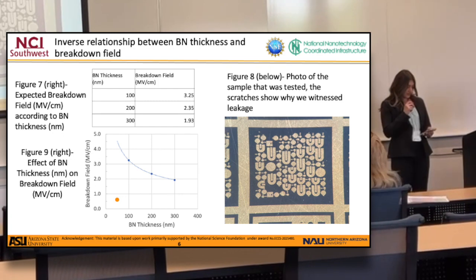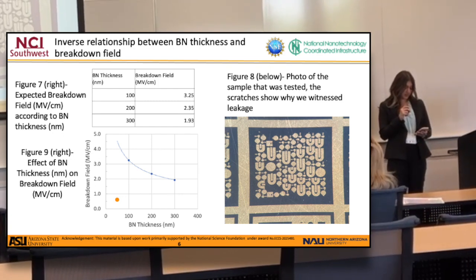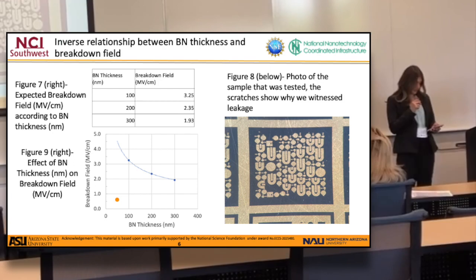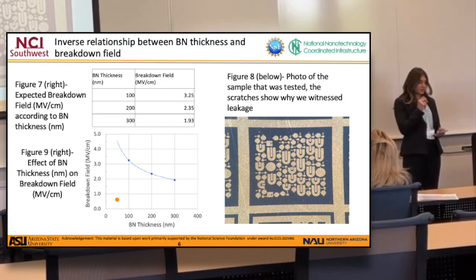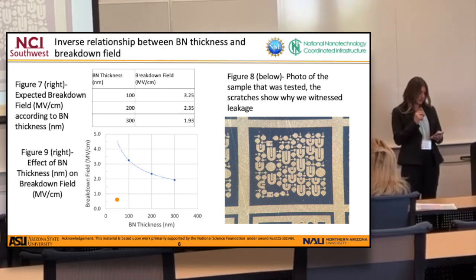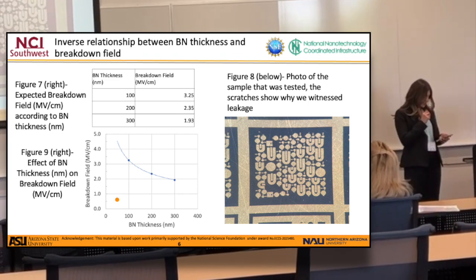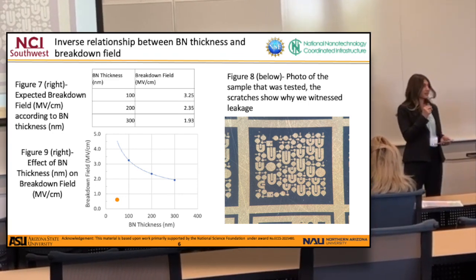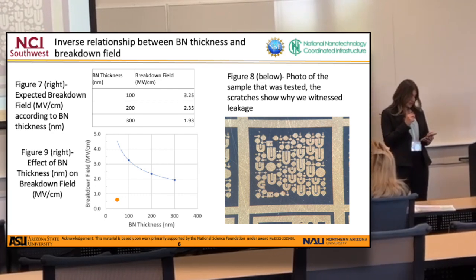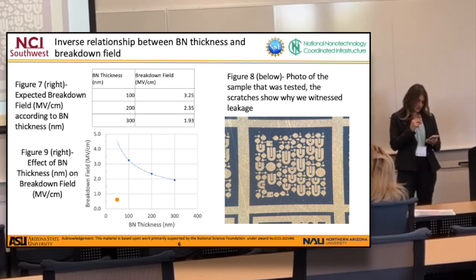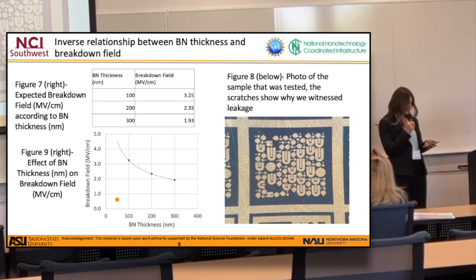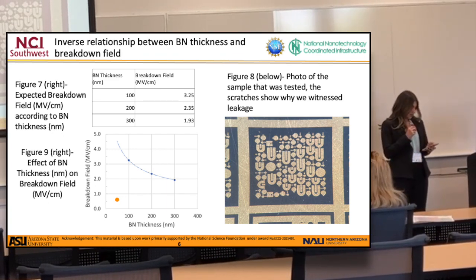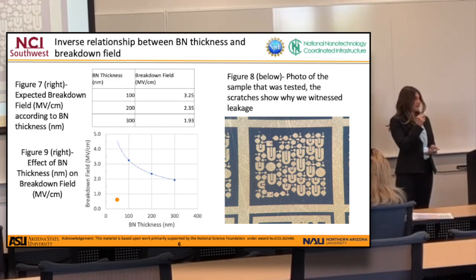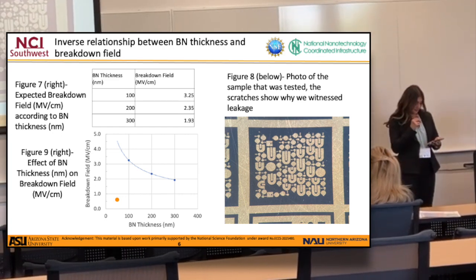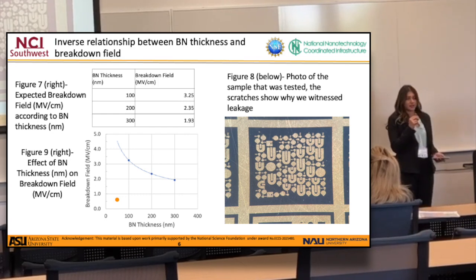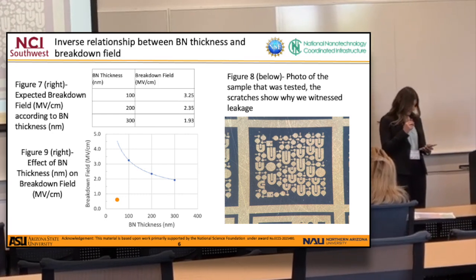To our understanding, we have so far established that as boron nitride thickness goes up, breakdown field goes down. However, during experimental research, we have noticed that the breakdown field was much lower when testing the 50 nanometer thickness than what we would have expected so far. The reason this pattern is going downwards is because there are small scratches in our sample which can contribute to defects during measurement. And these scratches are shown in figure 8. They're very faint, but you can kind of tell that they're there. So we're assuming that there's an outlier at the 50 nanometer point for this reason.